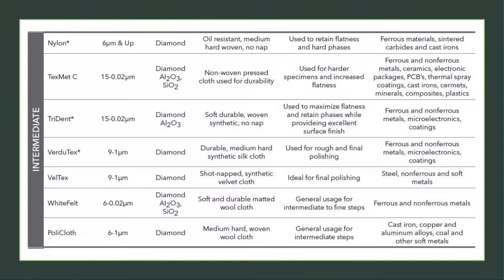So these are some of the different types of polishing cloths used for the intermediate polishing process. You can see that nylon pads are good for 6 micron and up diamond. They're oil resistant, medium hard woven, no nap. This helps retain flatness and hard phases, and it's great for ferrous materials, sintered carbides, or cast irons. So you see how each of these is good for whatever you're looking at preparing.